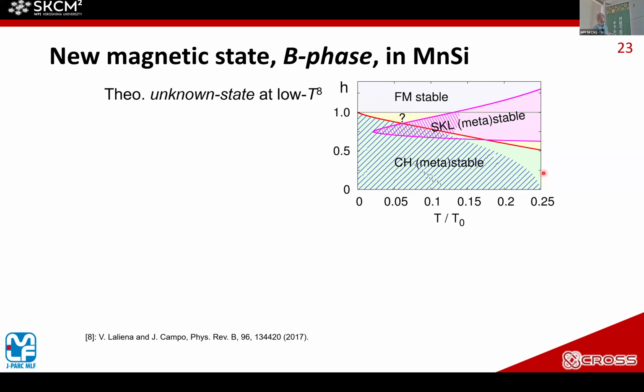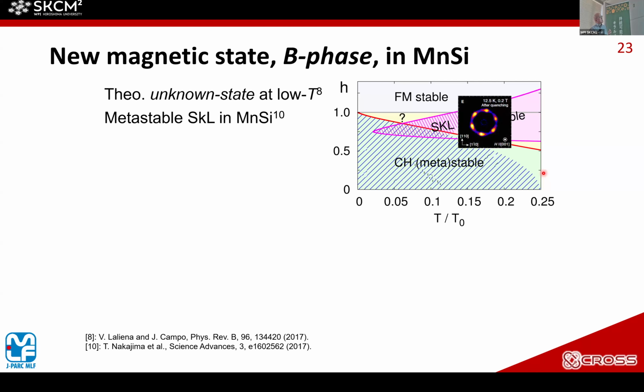On the other hand, theoretically, in 2017, a new state was suggested at low temperature and high magnetic field region. So this is a phase diagram of magnetic field and temperature. And here they suggest the unknown state at the low temperature region. And also, they suggest a metastable skyrmion lattice even at low temperature. After that, one measurement in manganese silicide said that there is a metastable skyrmion lattice even at low temperature.